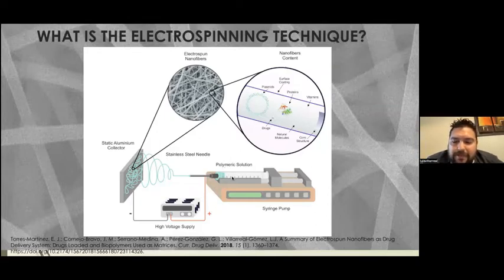You put it on the syringe pump, and you inject this polymer solution at a certain rate, milliliters per hour. Then you use a metallic collector in order to attract the future fibers, and you use a high voltage supply. So you connect an electrode to the stainless steel needle and another electrode to the metallic collector, which usually we make of aluminum, but you can use different kinds of metals. Because we prepare these nanofibers for biomedical applications, for us the best option is to use aluminum.